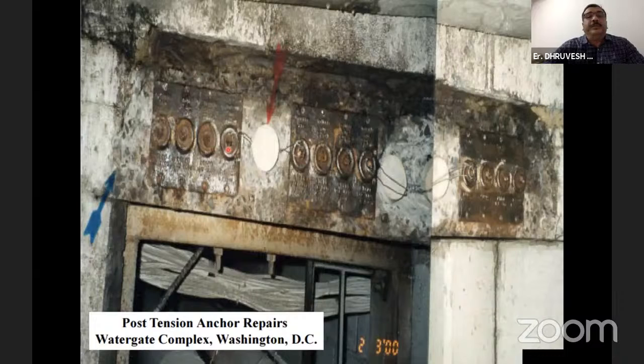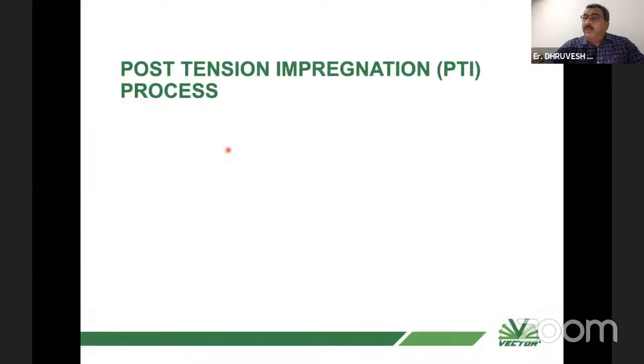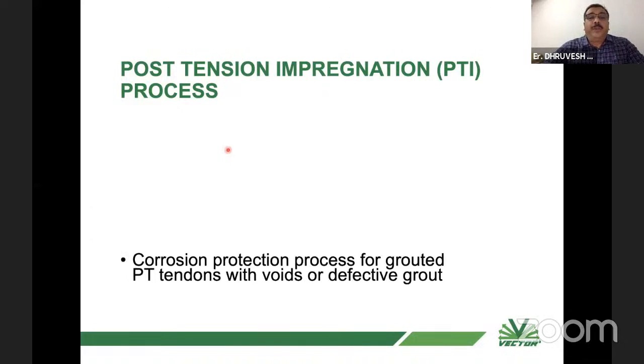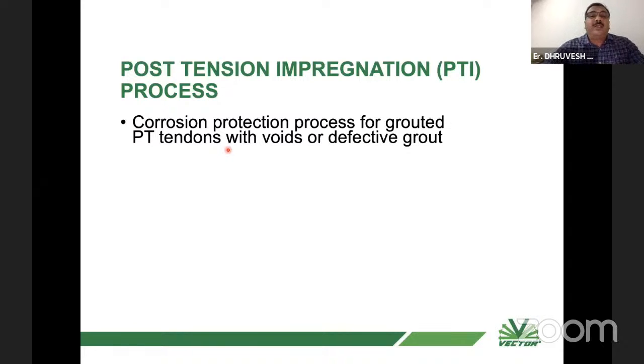Now, when you know that there are voids and ongoing corrosion, which is detrimental to my structure, and I want to protect my strands from further corrosion, obviously I cannot reverse the corrosion, but we can still retard the corrosion rate, up to 100 times less. So definitely it will enhance the durable functional life of the strands.